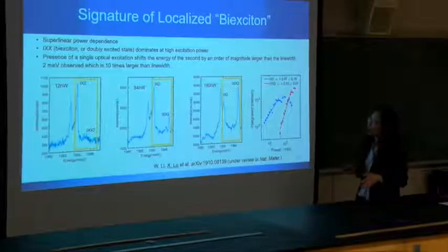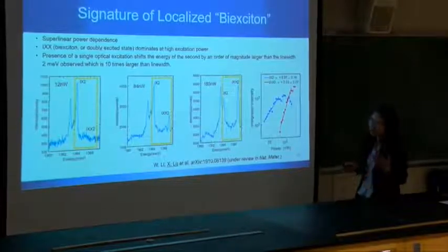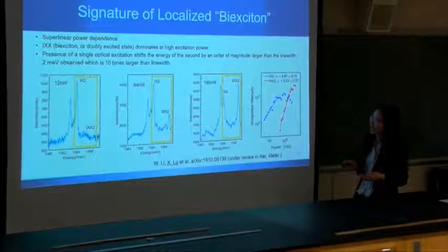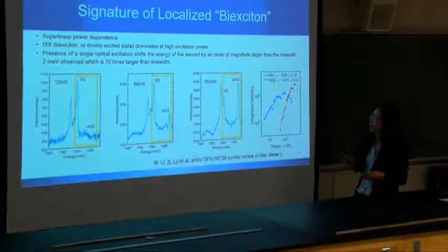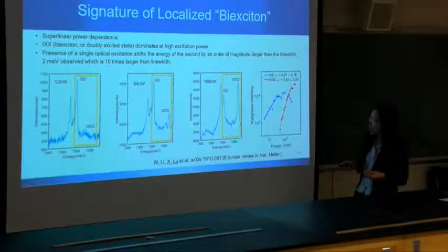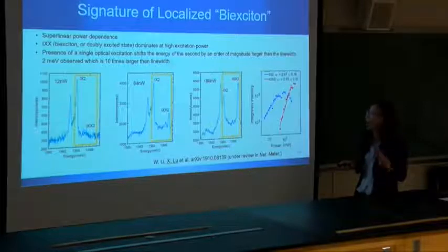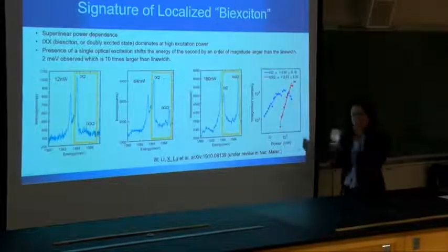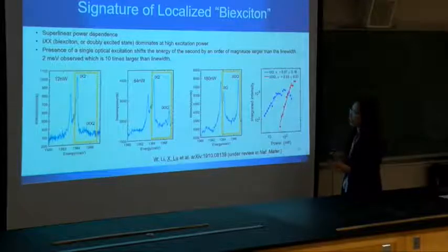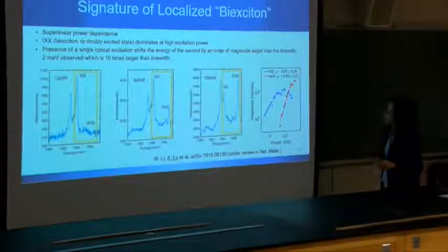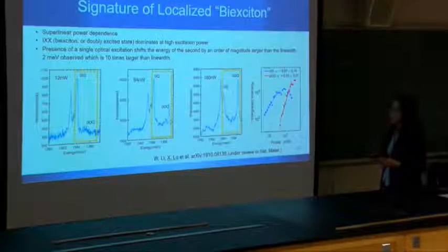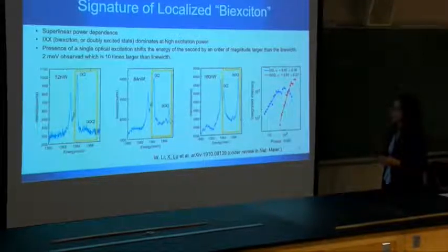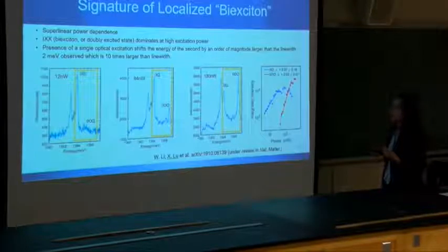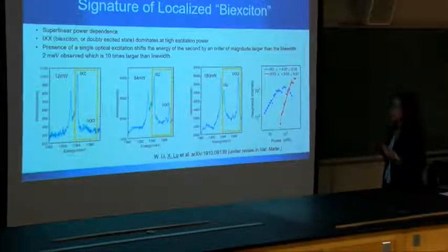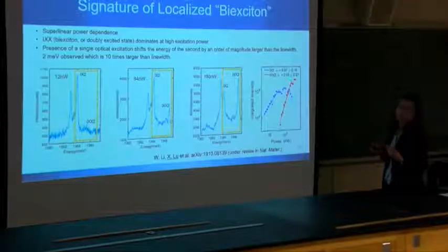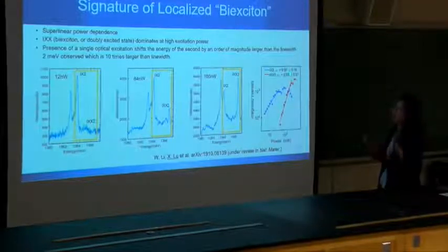And in our sample, we do observe this bi-exciton or doubly excited state. As you can see here, we label it as I double X. And it is at higher energy, about 2 milli-electron volt higher. That's because of the on-site repulsive interaction, we need to pay the cost. And then if we extract the integrated intensity as a function of power and fit the data with the power law function, we found that the coefficient of I double X is roughly 2 times that of IX. That's actually an indication of bi-exciton.